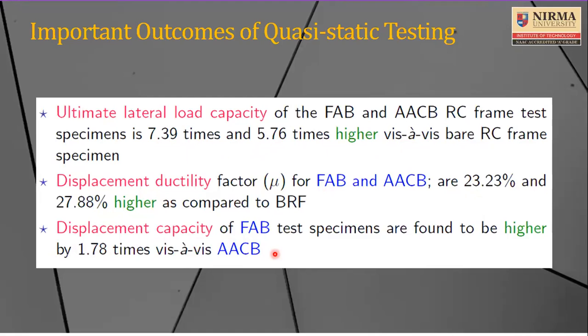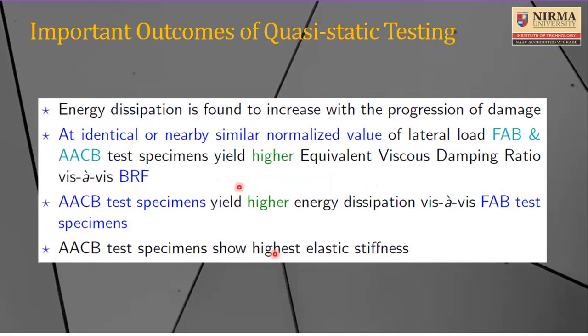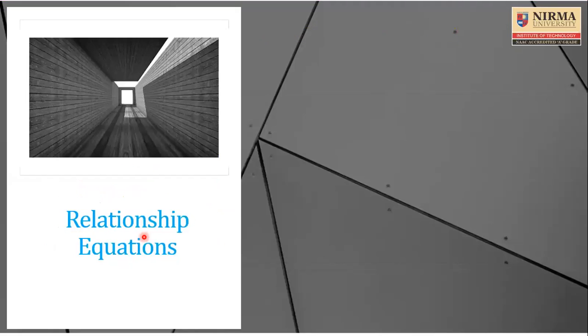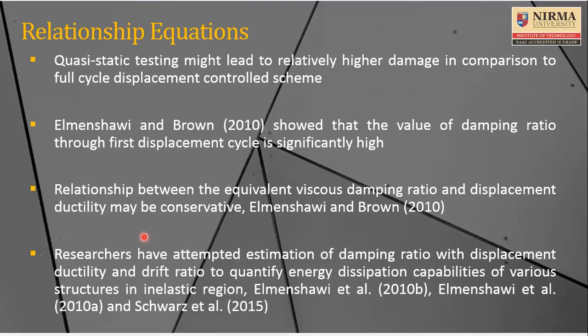But the displacement ductility, to our surprise, comes out to be a little better for fly ash brick as compared to AACB. But the damping capability of AACB is better than fly ash brick. So that we were also able to see. AACB test specimen gives higher energy dissipation vis-a-vis the fly ash brick test specimen, and the AACB specimen is higher as compared to fly ash or even red clay brick. Based on that, we understand that not only stiffness is important, but damping plays a very, very important role in seismic analysis.